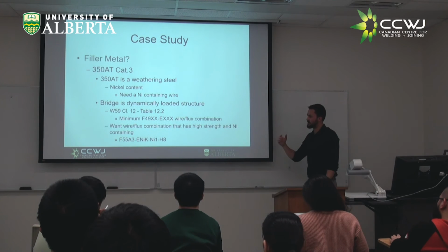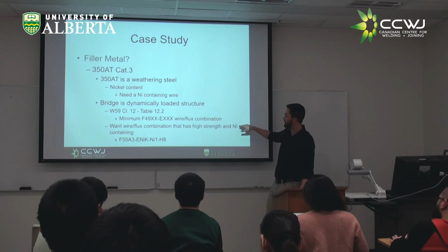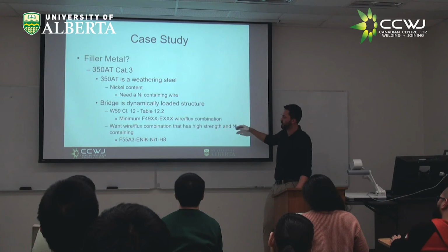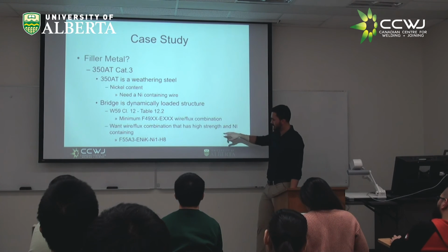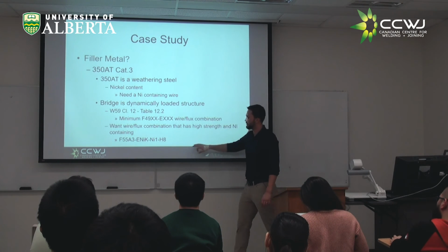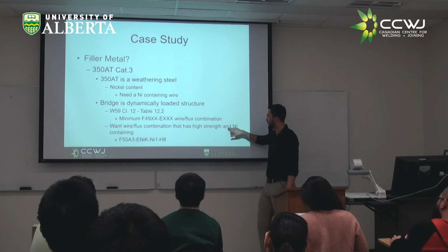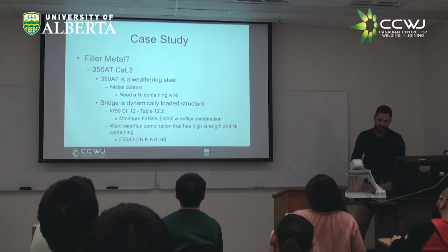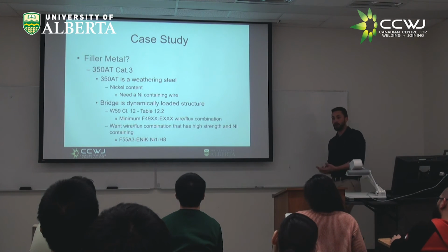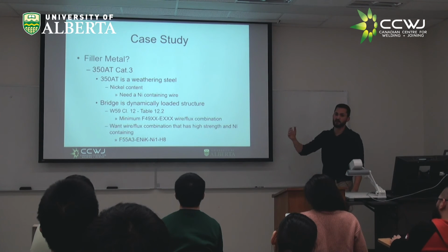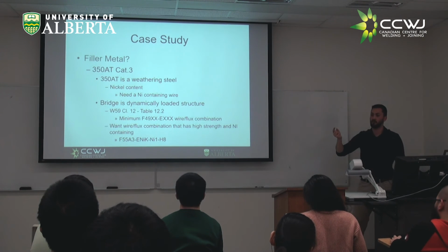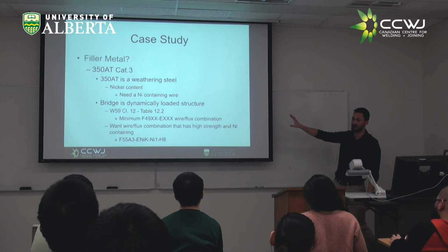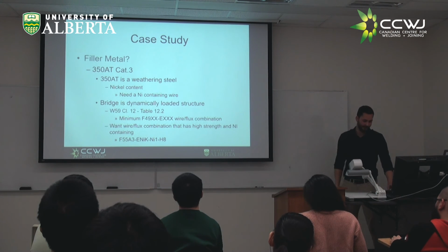But in reality, we actually tend to use a higher strength, and the designers like this. We tend to use a little bit of an overmatch for the base material strength, and we tend to use this sort of 55 KSI wire. And we also need a nickel containing wire because we need to make sure that our weld rusts as well. Because if your weld doesn't rust by itself, because it has nickel in it, it's going to rust and then it's going to fail because that rust isn't going to stop.